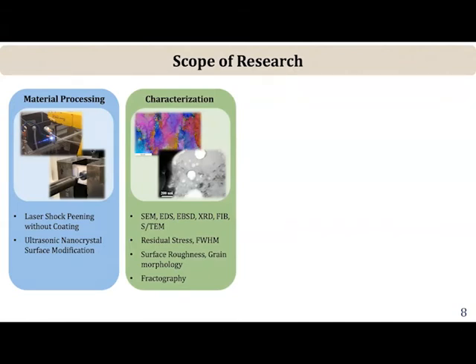Characterization of microstructure and residual stress using a host of techniques, typically scanning electron microscopy, energy dispersive spectroscopy, electron backscatter diffraction. And then also to look at the near surface microstructural changes, you use focused ion beam methods to extract thin foils from the near surface regions, so that we can understand those microstructural changes in much more detail. Residual stresses measured by X-ray diffraction, characterizing surface roughness, grain morphology, and then fractography as well.